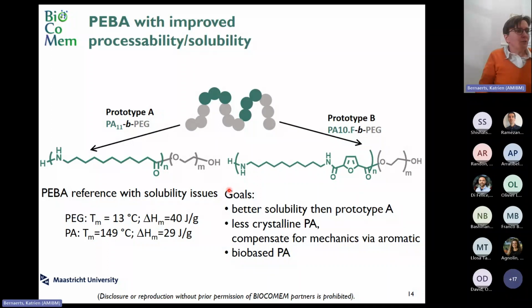Therefore, we decided to make polyamide based on C10-diamine and furan, which are bio-based building blocks. Of course, the crystallinity is needed for the mechanical properties of the membrane, but the hypothesis is that by using some aromatic groups, we have a way to compensate for the loss in mechanics due to reduced crystallinity.